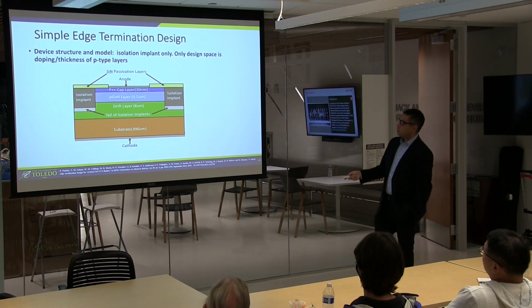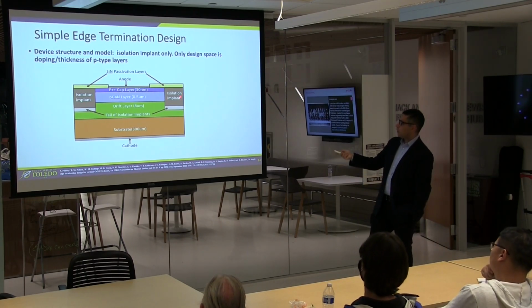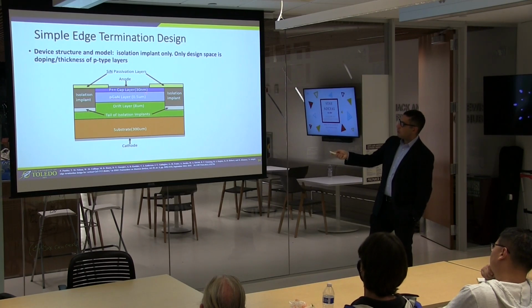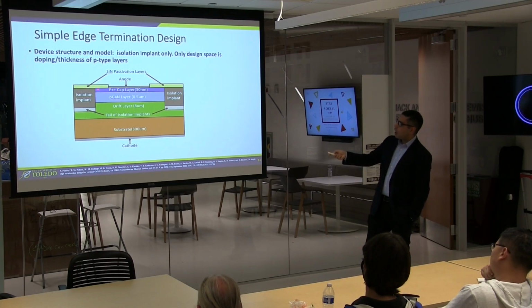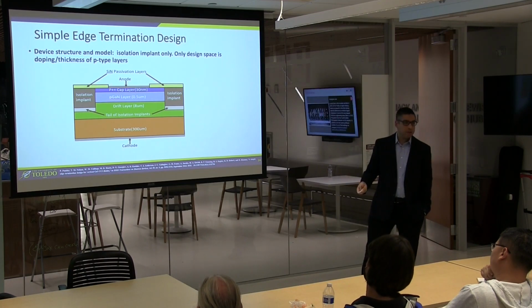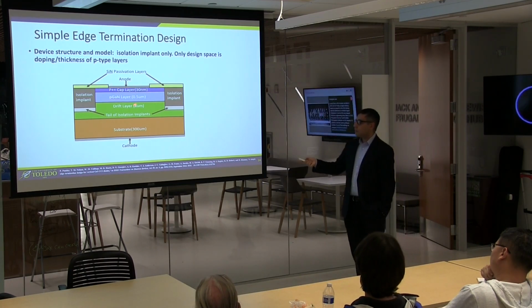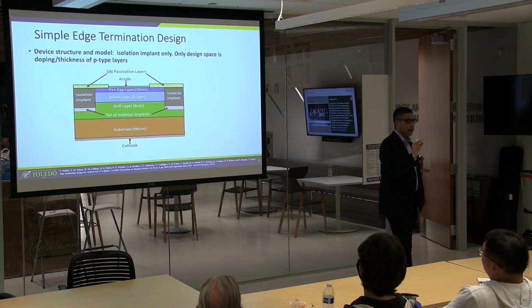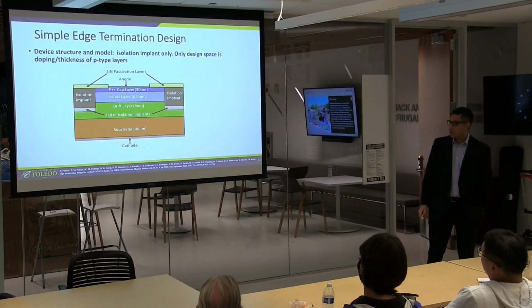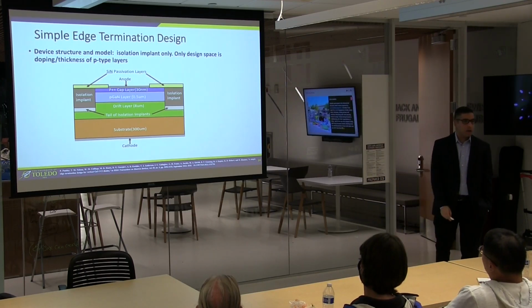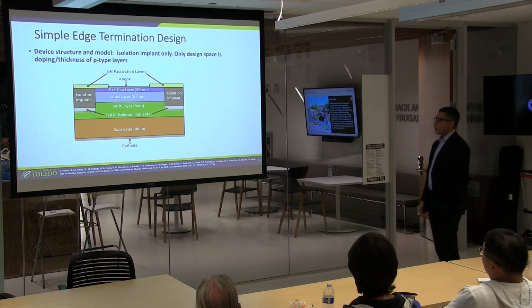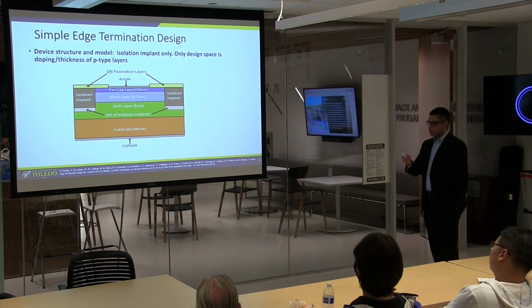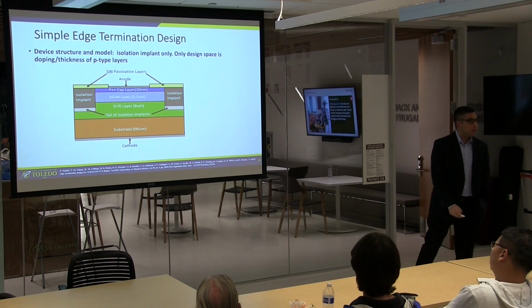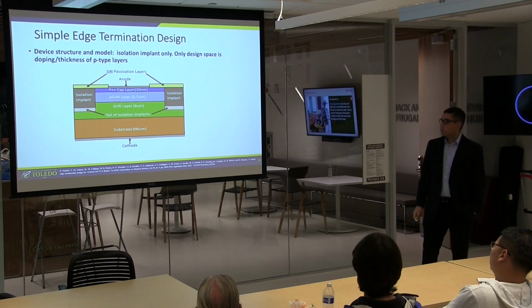I call your attention to just a simple isolation implant here on the side. There's a P++ capping layer underneath the anode that extends underneath the silicon nitride passivation layers. That P+ capping layer is hopefully to form a smaller contact resistance, but we find that it plays another role, and I'll show you that in a minute. So they gave us this structure, and they asked us to model it in TCAD, finite element modeling.